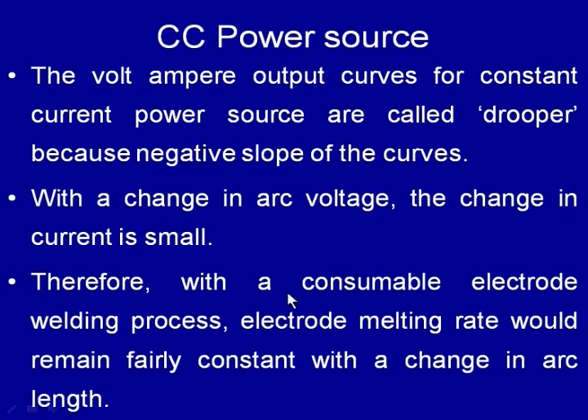The volt-ampere output curves for a constant current power source are called droopers because of their negative slope, and that is why these are called the drooping characteristic of the power sources. With the change in arc voltage, the change in current for this type of power source is very small. Therefore, with consumable arc welding processes, the electrode melting rate would remain fairly constant with the change in the arc length, because heat generation is governed by the welding current, and the welding current remains constant even with the change of the arc length.